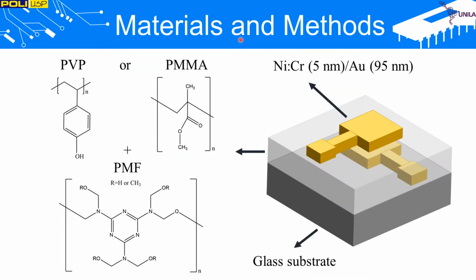The device structure and the chemical structure of organic molecules are presented in these figures. PVP and PMMA molecules were cross-linked with PMF molecules at different ratios. Metal films for capacitors were a 5 nm thick nickel-chromium adhesion layer, followed by a 95 nm thick gold layer by DC sputtering. Electrodes were patterned over glass substrate by photolithography, followed by etching.